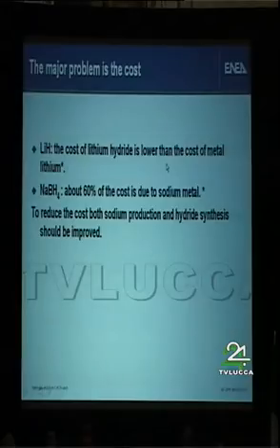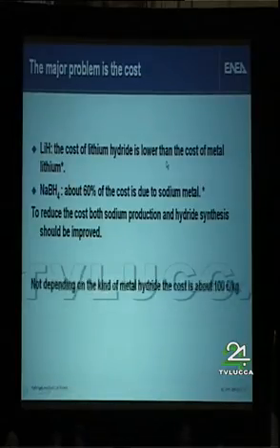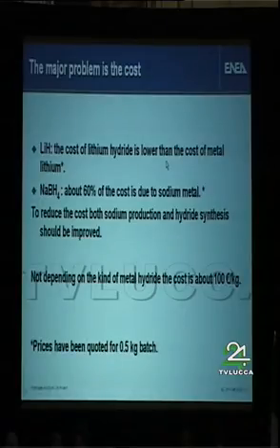The cost of lithium hydride is lower than the cost of metal lithium. And for sodium borohydride, 60% is related to the cost of sodium metal, and to reduce the cost, both sodium metal production as well as a new synthetic way should be found. Roughly speaking, not depending on the kind of hydride, the cost of hydride is about €100 per kilogram.